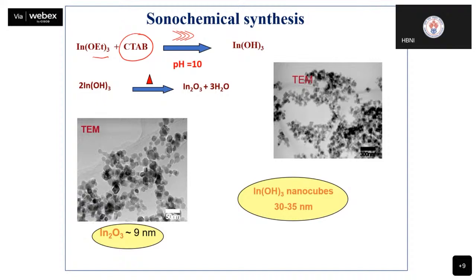And there are many more surfactants that people use. So indium ethoxide and CTAB were taken in solution at a pH of 10 because I want hydroxide. We passed ultrasonic radiation and this product was obtained. This product was filtered, centrifuged, and washed and then heated. Upon heating, it gave indium oxide, nano indium oxide. So this is a TEM image of your indium hydroxide nanocubes, which have a size of 30 to 35 nanometers.